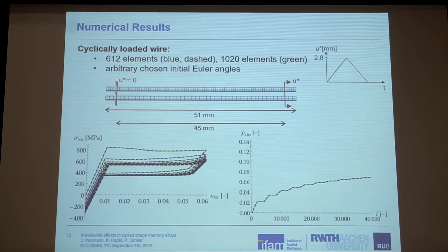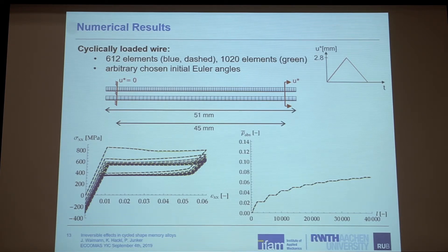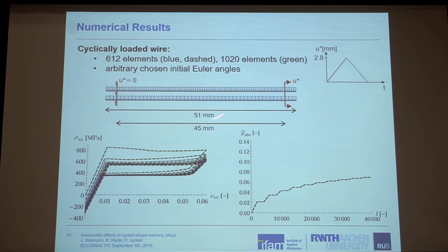Now our material model is set, and we can look at some results. Here we can see a cyclically loaded wire with two different meshes and the resulting stress-strain diagram. The initial Euler angles are randomly chosen for the first example, then they correct and converge to the converged solution. We can see the material behavior also observed in the experiment: the decrease of the plateau stresses, particularly the upper one, and the formation of remaining strain. The large drop between the first two cycles is due to the initial choice of Euler angles. Our results are mesh-independent for both meshes, and we can see that the absolute value for the total martensite is converging.